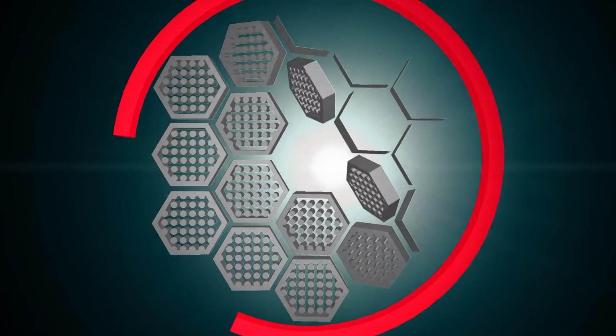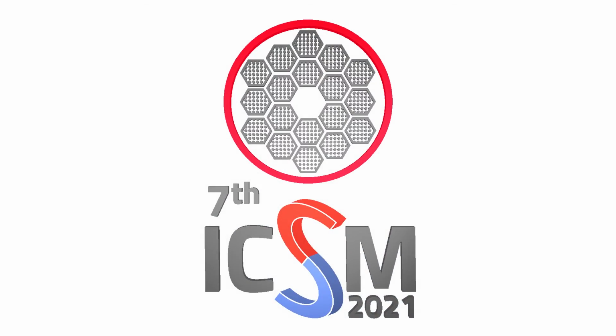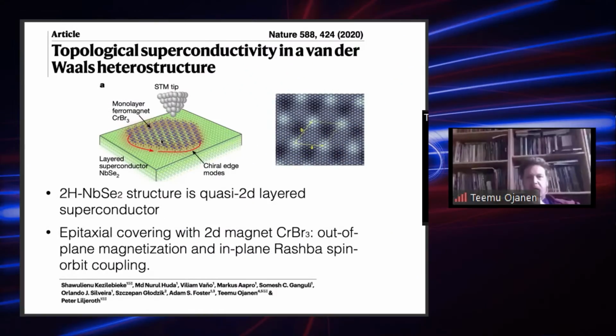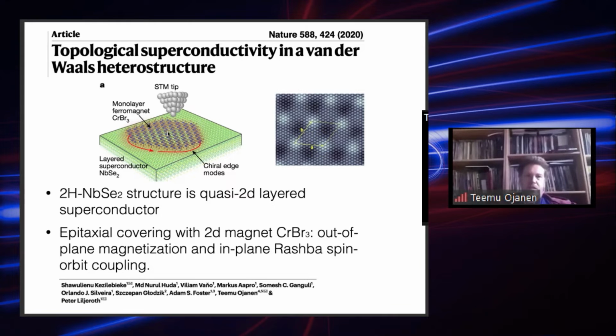And what this additional chromium tribromide monolayer here does is that it provides an out-of-plane magnetization on the top, on the area where it's covering the niobium diselenide, and then it possibly also supplies the system with the Rashba spin orbit coupling, because it's breaking the mirror symmetry with respect to the surface plane. So it brings two additional features to the pristine niobium diselenide: the perpendicular magnetization and Rashba spin orbit coupling. And these are, of course, the two ingredients in addition to S-wave superconductivity that people think provides us a route towards P-wave superconductivity or chiral superconductivity in 2D systems.